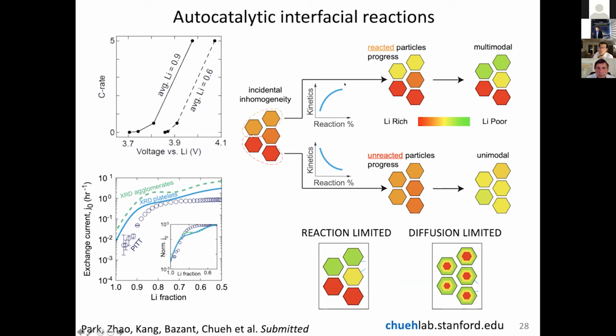And that's what I'm showing here on the top row. This is where you are getting faster kinetics with the reaction extent. This is autocatalysis. But now if you do everything in reverse, now you are putting lithium back in, the kinetics actually slows down. So any heterogeneity you have initially actually gets diminished. So this is the autoinhibitory effect.